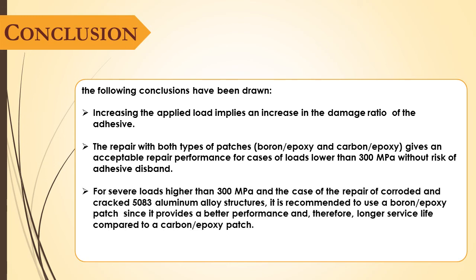For severe loads higher than 300 megapascal and the case of the repair of corroded and cracked A5083 aluminum alloy structure, it is recommended to use a boron epoxy patch since it provides a better performance and therefore longer service life compared to a carbon epoxy patch.